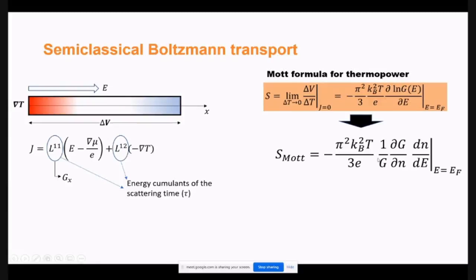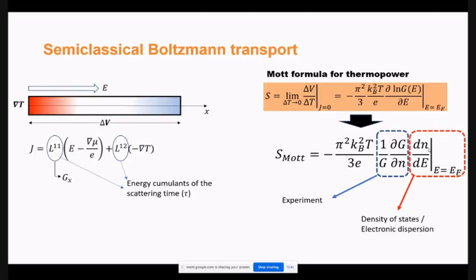two parts, which is (1/G)(dG/dN), which is determined from experiments, because we are always measuring conductance as a function of gate voltage, and gate voltage essentially changes the density. So (1/G)(dG/dN) is essentially an experimentally determined number, and dN/dE is essentially a number which is given by the density of states, okay, the number of states per unit energy at the Fermi energy. So if you know these two from your system, then you should be able to predict the Mott or the thermoelectric figure of merit of a system.